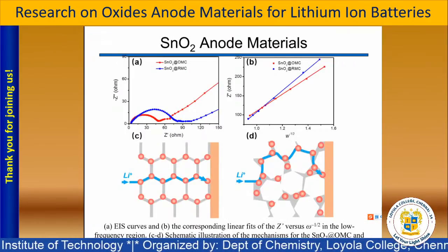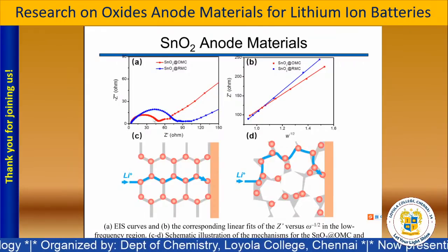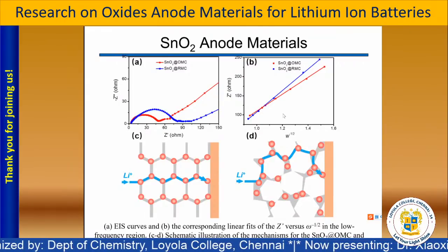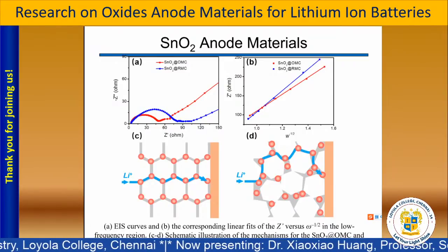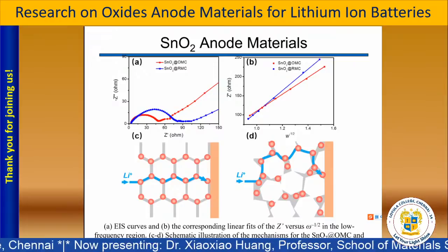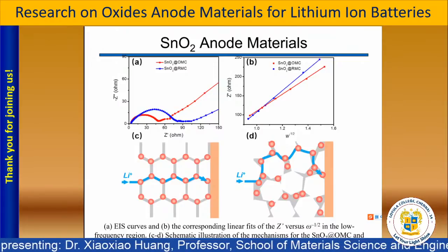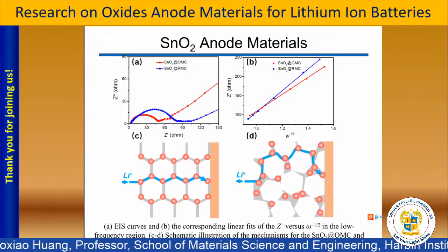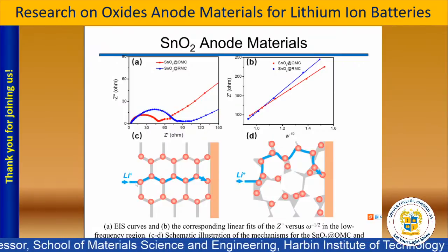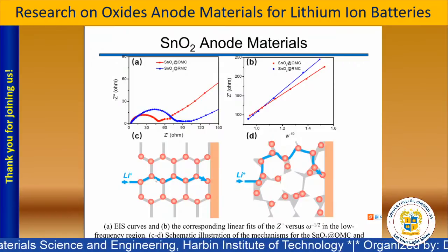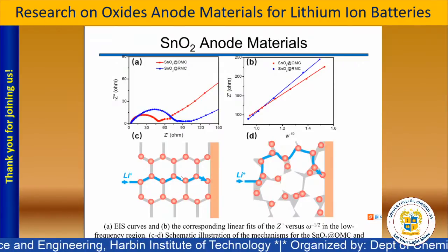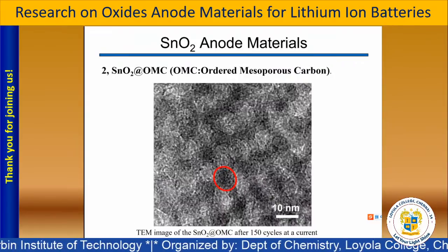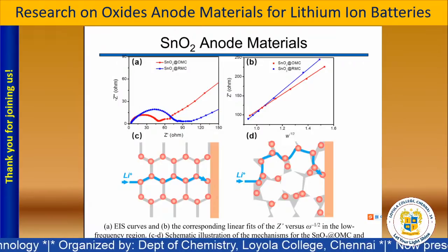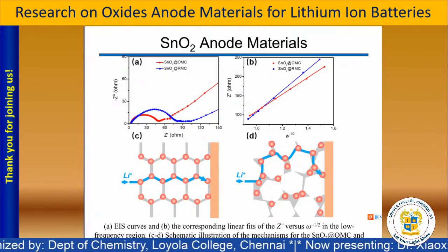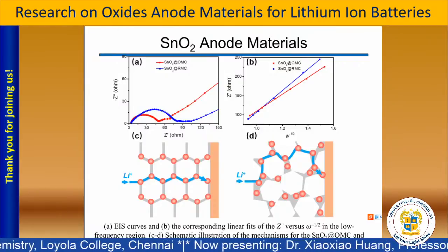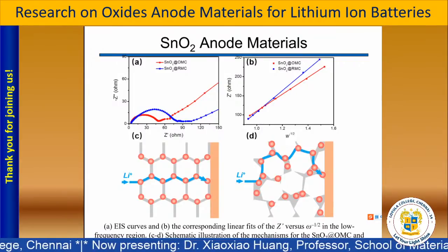The EIS curve tells us about the conductivity and the diffusion efficiency, and we also calculate and test the OMC structure. It is beneficial for lithium ion transportation. That means the material can be uniformly wetted by the electrolyte, which shortens the transportation distance and gives improved performance.